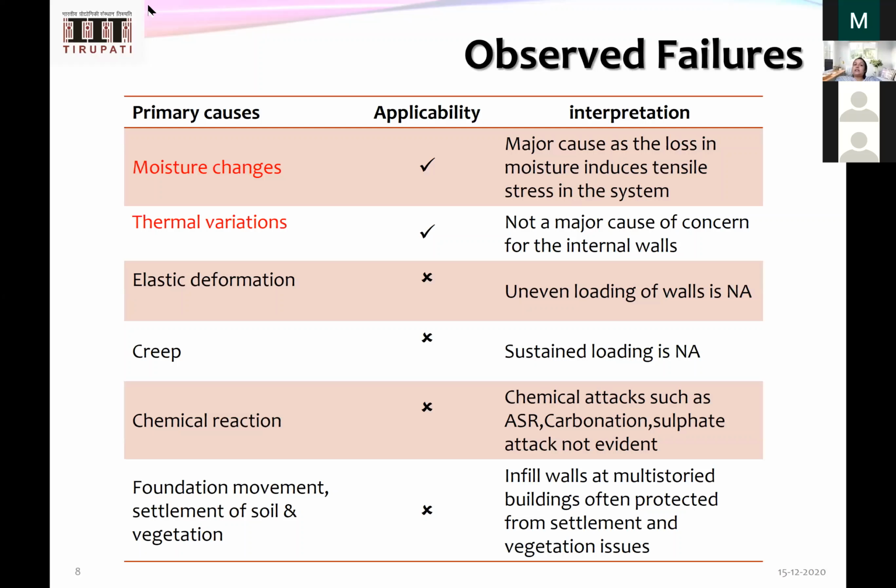So what we understood is, in this particular situation, AAC blocks have been used as partition walls. There, elastic deformation, creep, chemical reactions and foundation movements are not observed. Especially creep is not going to be there. There is no sustained load in it. It's a non-structural element. You have moisture changes and thermal variation. These are the two possibilities.